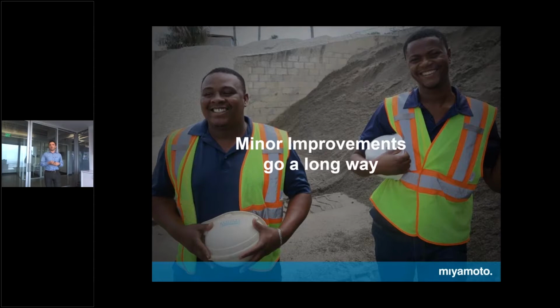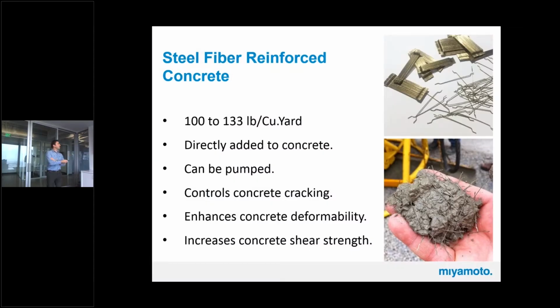And we know that concrete crushes, okay? But we don't want to invest too much and use dampers or isolators. Fibers are one of those that, by minor improvement, you can get higher return. So we specified steel fiber reinforced concrete, okay? Based on the literature and also our investigation about the performance of the structural elements with different dosages of the fibers, we specify 100 to 133 pounds per cubic yard of concrete.